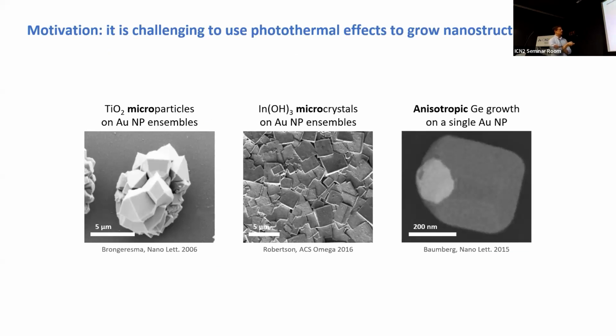Many people had tried to use light to grow materials controllably at the surface of plasmonic nanoparticles. However, it's kind of complicated. So typically you get larger structures, not very well controlled. There are probably some particles inside these large crystals. There are definitely particles here suspended on a substrate, and they were growing indium hydroxide microcrystals.